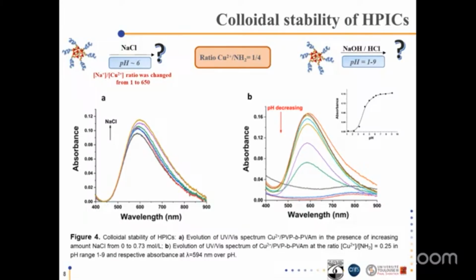So we can say that the stability of HPICs isn't governed by electrostatic forces, but rather by steric stabilization provided by the hydrated neutral corona. Additional experiments were conducted to evaluate HPICs' colloidal stability over a pH range from 9 to 1, figure 4B. With pH lowering, we observed a decrease in the copper binding band caused by decomplexation. From pH 9 to 6, the absorbance of HPIC solution remains roughly constant, suggesting the complexes remain intact.